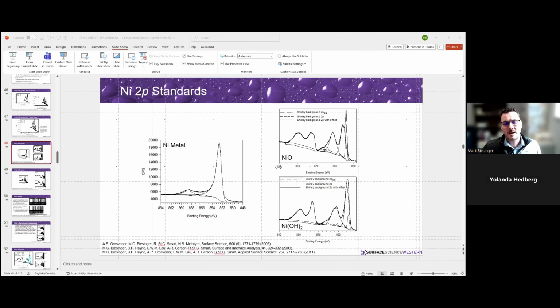There is a peak in my carbon high resolution spectrum in the binding energy of lower than carbon-carbon, lower than 283 eV. What can be related to? That's typically a carbide. And so if you have a metal, you can have these carbide formations. They are going to be at that position around 283, 283.5, somewhere in that range. So that's a carbide. It's not an organic peak. Easy question.